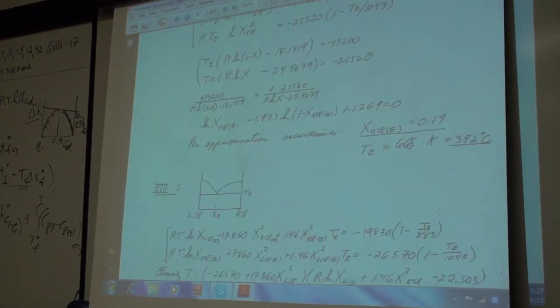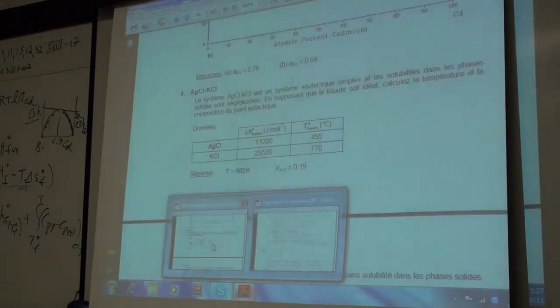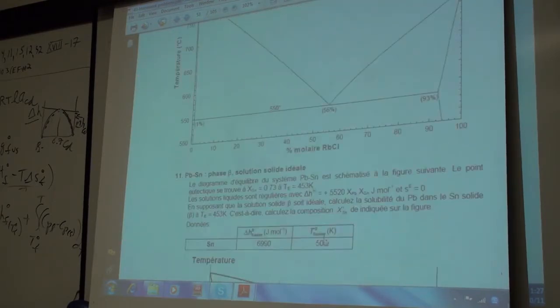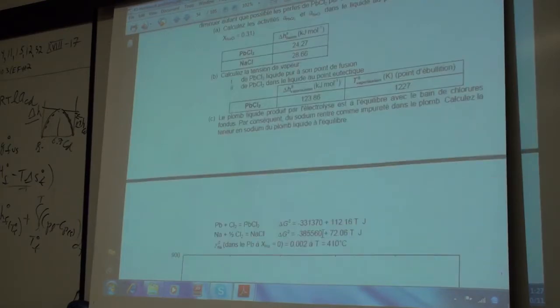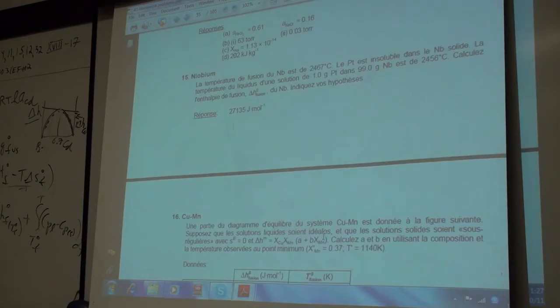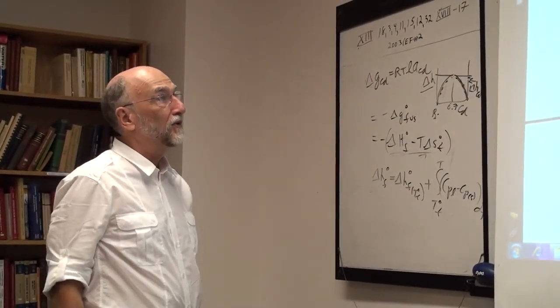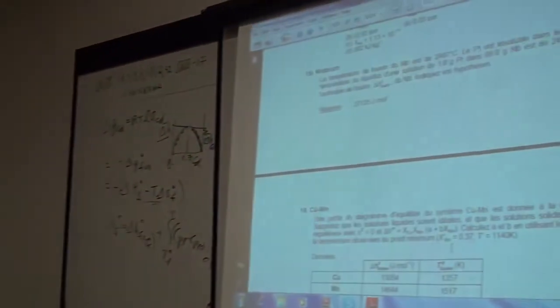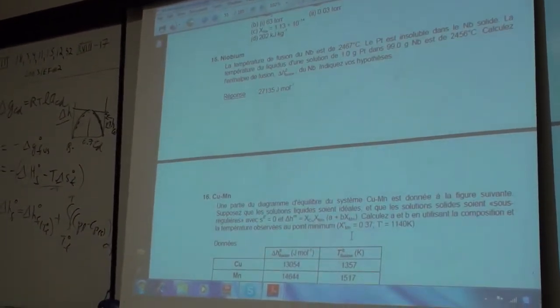All right, if you go to number 15, this is the one we talked about at length last week, that you can actually use the equation going the other way around. You can use a liquidus measurement in the dilute region in order to measure a heat of fusion, which is often very difficult to measure at very high temperatures. So the melting point of niobium is very high, 2467 degrees Celsius. Platinum is insoluble in solid niobium. The liquidus temperature when you have 1 gram of platinum and 99 grams of niobium is 2456. Calculate the heat of fusion, the enthalpy of fusion of niobium.